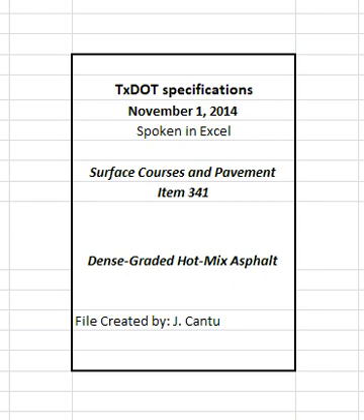4.4.2.1.6 Ignition oven correction factors. Determine the aggregate and asphalt correction factors from the ignition oven in accordance with TEX-236-F. Provide the engineer with split samples of the mixtures before the trial batch production, including all additives, except water, and blank samples used to determine the correction factors for the ignition oven used for QA testing during production. Correction factors established from a previously approved mixture design may be used for the current mixture design if the mixture design and ignition oven are the same as previously used, unless otherwise directed.